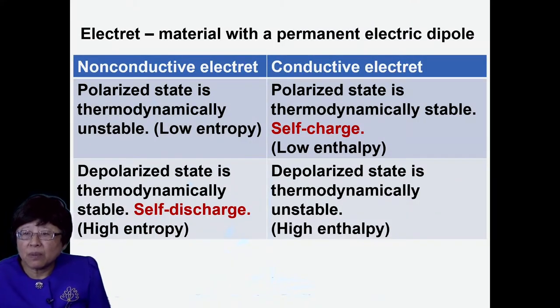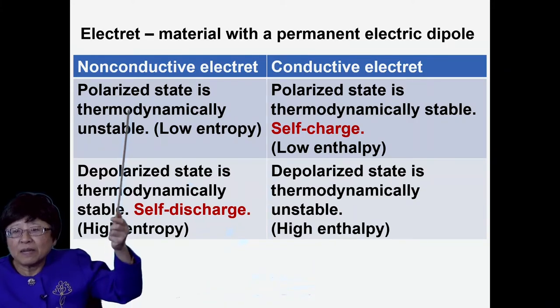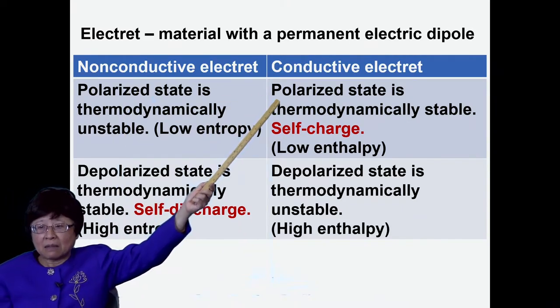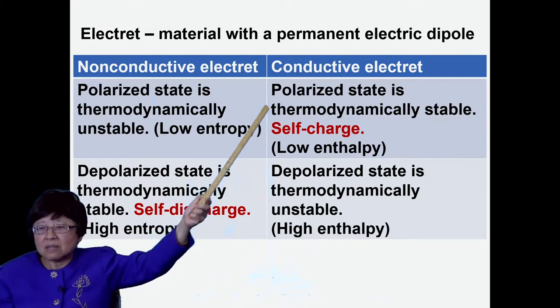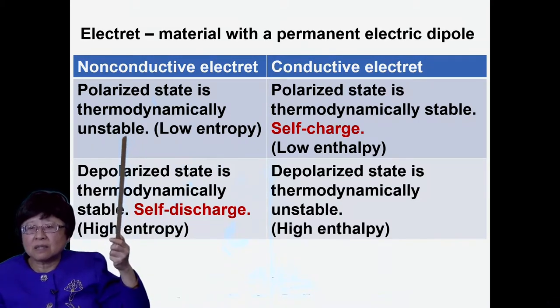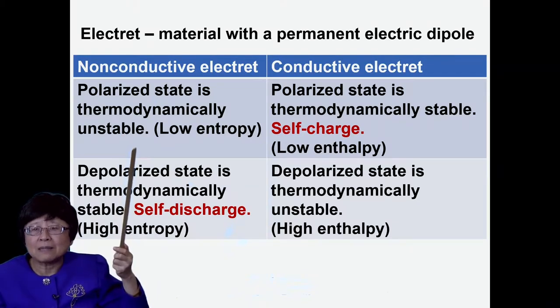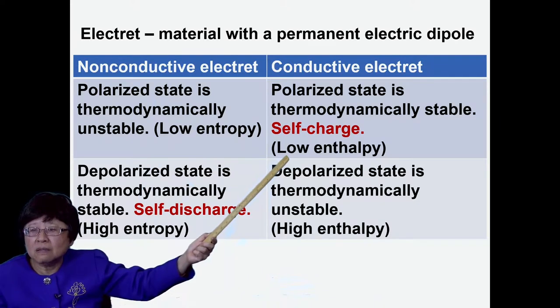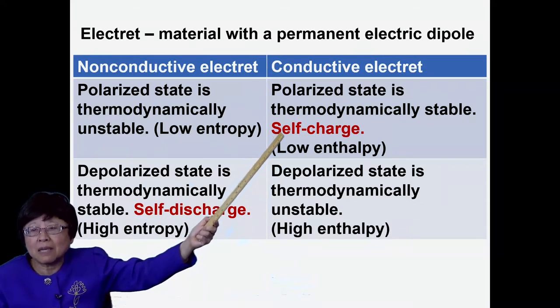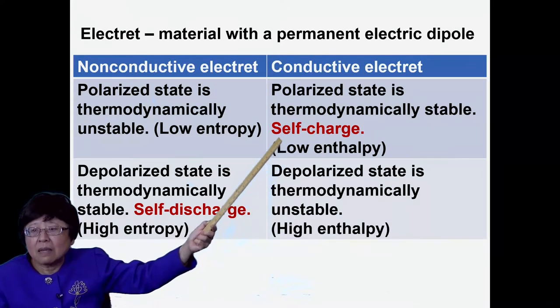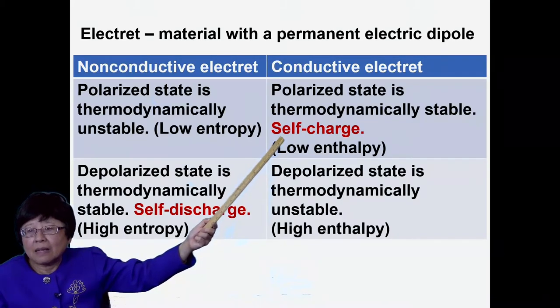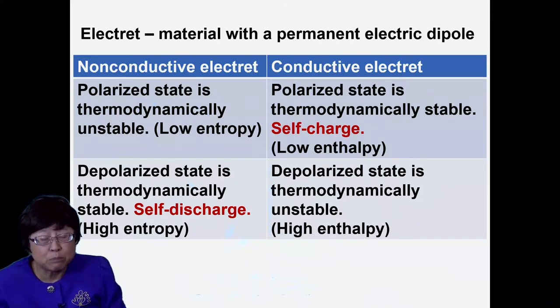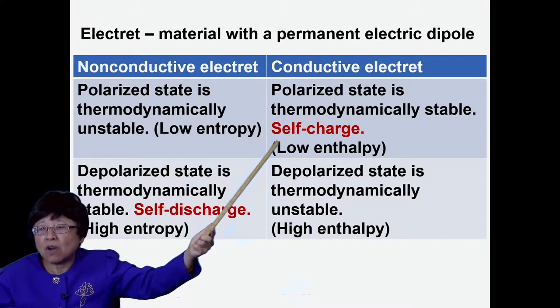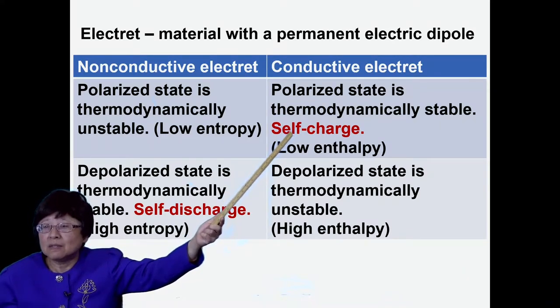So electrets are materials with permanent electric dipoles. And they have been around among non-conductors for a long time, but not among conductors. That's a new thing. Conductive electret is the new thing. For the non-conductive electrets, the polarized state is thermodynamically unstable because of the low entropy. But for the conductive electrets, the polarized state is thermodynamically stable because of the low enthalpy. As a result of that stability, it can undergo self-charge. That is, if you discharge it by brute force, short-circuiting, and then open-circuit it again, and let it sit, it'll automatically charge back. That's called self-charge, and that is feasible because the polarized state is thermodynamically stable for the conductive electret.